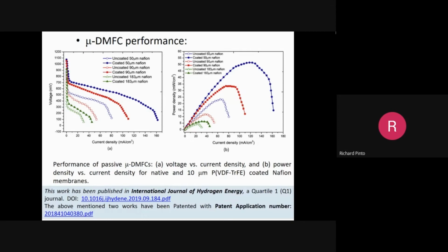Now, that slide was shown earlier, but I'm repeating it here. What is the benefit? Proton conductivity is not reduced very much. It's almost the same as the uncoated membrane, but at the same time, permeability of methanol is reduced significantly. And that should be seen in the power; the proof of the cake is in the eating. So you get the power density plot here. You see here, voltage versus current density, in milliamps per centimeter square, and the power density plot here. Voltage drops as you draw current, which is all standard. But you see the power density plot.